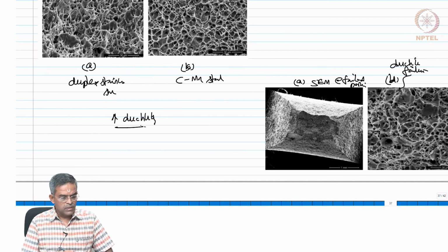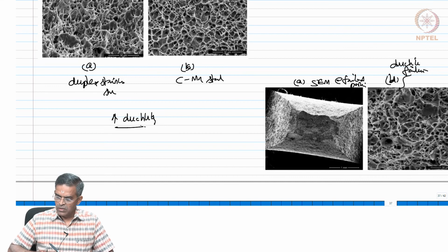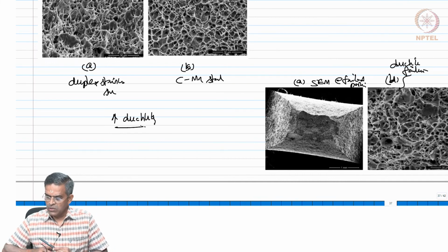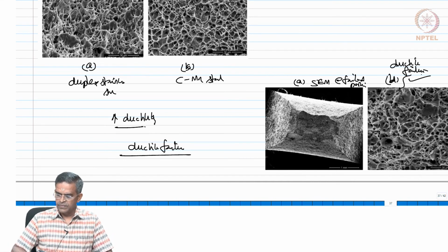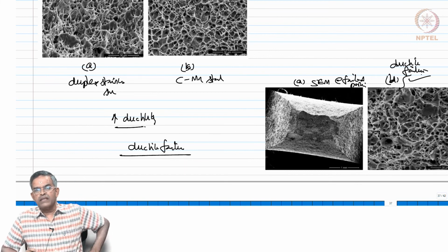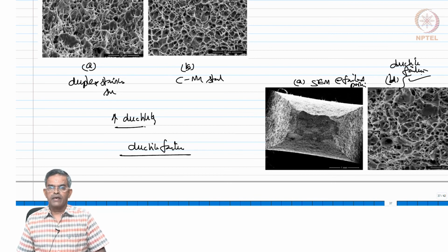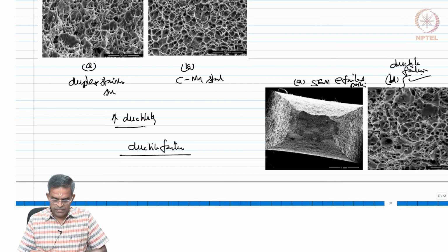Furthermore, the stress partitioning was shown through an SEM image between the two materials, which shows that the failure is purely a ductile failure. So, the ductility characteristic of FGM is not compromised by mixing or by functionally grading these two materials.